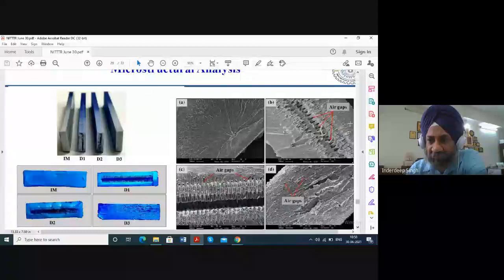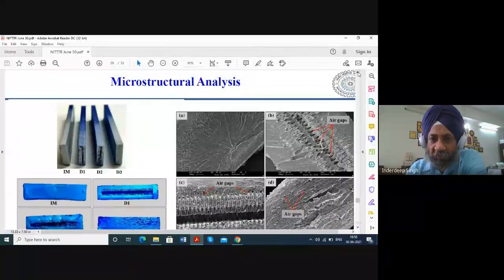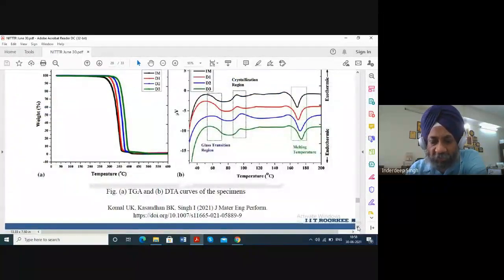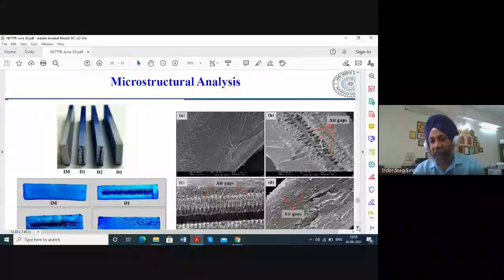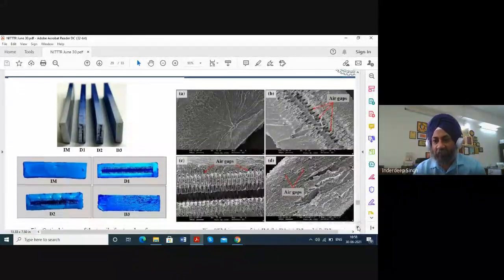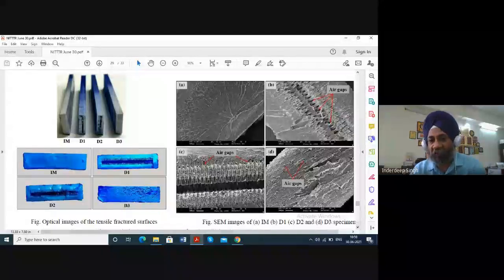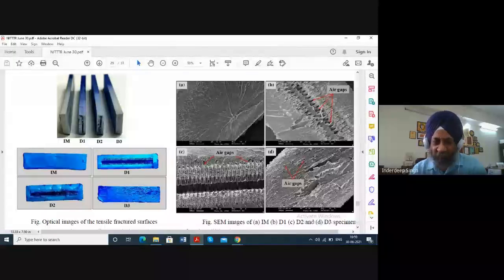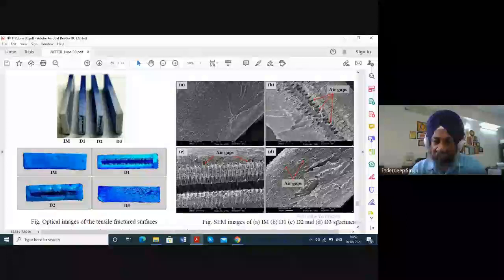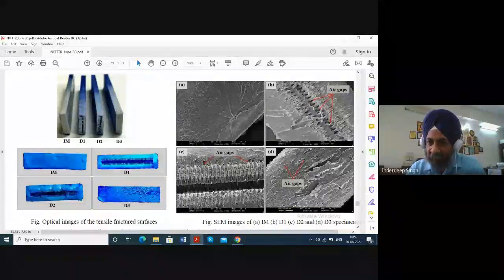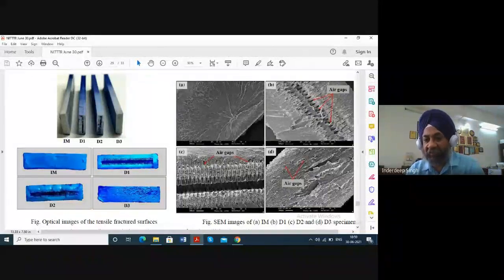And these are the microstructural analysis of the samples that we have done, and we can see that there are a few air gaps, FE images. This first one is the injection molding. Then this is D1, which is fill density 80, D2 again fill density 90, but D3 with fill density of 100%. So we can see there are sometimes air gaps inside where the fill density is not 100%, but here we see a lesser number of air gaps in case of 100% fill density samples made by the FDM process.